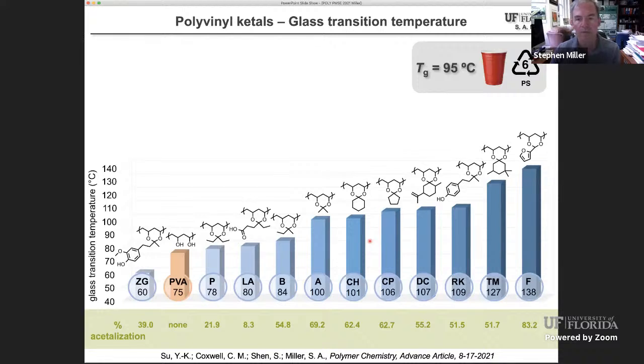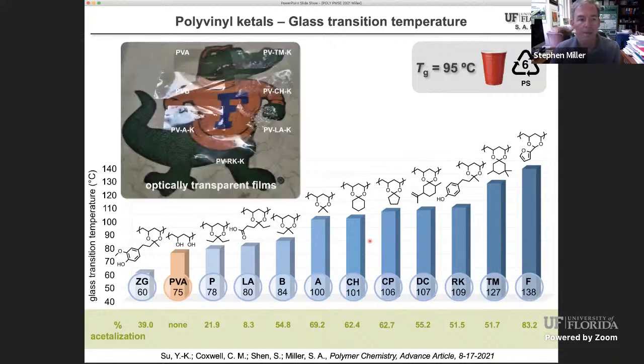We can dry them a little bit by water removal. We can make films out of these materials. So here is commercial polyvinyl alcohol. It's pretty clear. Commercial polyvinyl butyral, which I mentioned was an interlayer glass material, pretty clear. Our polyvinyl acetone ketal, also pretty clear. So these are solvent cast films, which we're able to make, some with more skill than others, but nonetheless, these seem to be pretty reasonable and strong, tough film-like materials that could potentially be used.